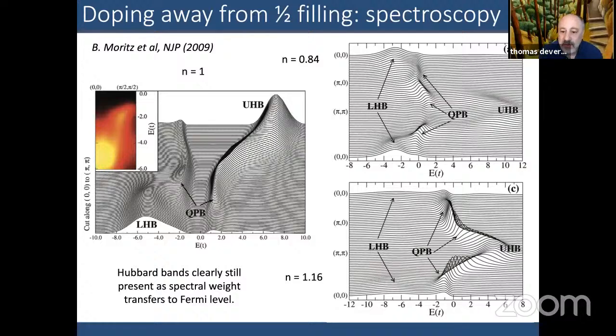And the other signature from the numerics is, of course, that this transfer of intensity occurs over large energy scales. And you can see that very clearly when one looks at photoemission. On the left-hand side is the insulator, where you have a gap at half filling, the lower Hubbard band prominent at momentum 0,0, and the upper Hubbard band prominent at momentum pi. And in between, a quasi-particle band that approaches the Fermi level but is gapped out. And that quasi-particle band, when doped, crosses the Fermi level and steals intensity both from the lower and upper Hubbard band when one dopes either with holes or with electrons, as you can see on the two plots on the right-hand side. So although spectral weight is still being transferred out when 16% holes or electrons are doped in, the upper and lower Hubbard bands are still clearly visible. So the physics of correlation is still there, and spectral weight transfer is still important over large energies at these dopings.